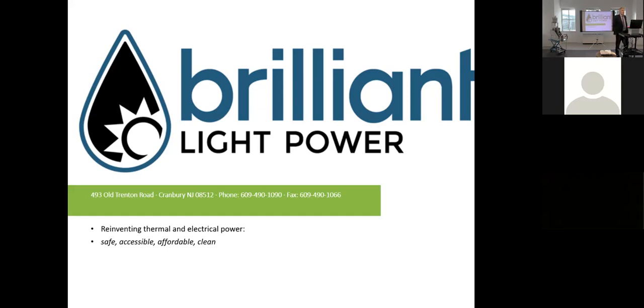Gallium has another unique feature. When it's run under a hydrogen atmosphere, even though there's some oxygen there, even in trace amounts, there is some water going into that stream, very trace amounts, and that will react with gallium to form a gallium oxide. But you can tell that it's not forming a permanent gallium oxide because we're continuously running current through it. As soon as it forms, a gallium oxide is an extraordinarily high insulator. You would not be able to put a current through it. As we found out, if you put in too much water, that can occur in seconds.